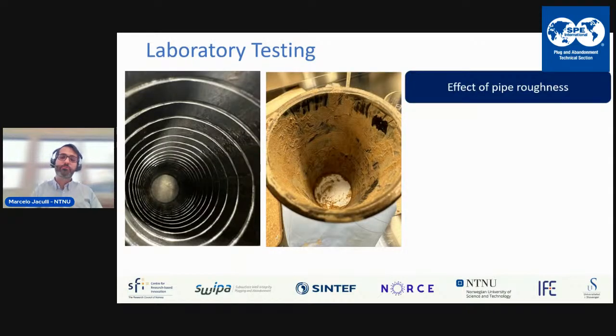Another thing that we tried was checking the effect of pipe roughness. We realized that there is a balance here between not having a surface that is too polished, because you want some friction, because essentially that's what's holding the plug in place. It's purely a mechanical effect, so it's the friction between the two metals that is keeping the plug in place.